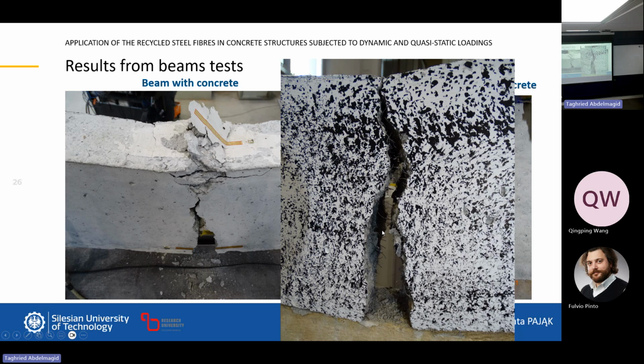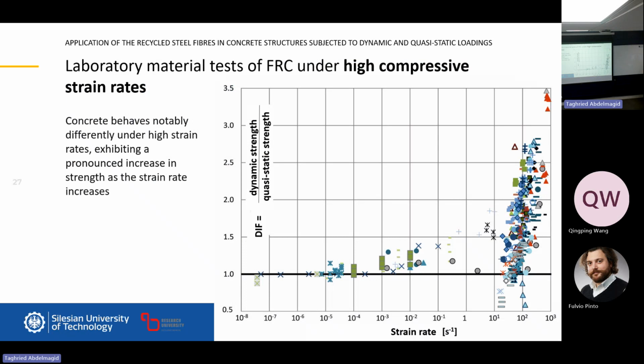They are working in this element. They are not so efficient because they are not too big. If they were bigger, longer, they would be more efficient. But in general, there are a lot of them, and it's very good. And coming back to the rheological parameters of the mix, we can't add more because 1.5% is the highest value. When we add more, the self-compacting concrete won't be able to be poured. So this is the highest amount of the fibers that we can use.